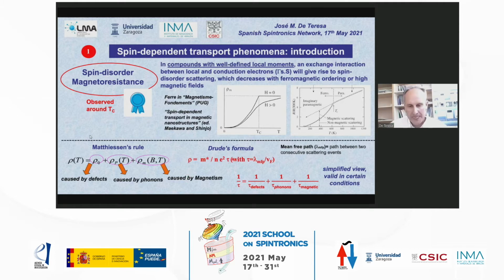To put it in simple words, if you apply Drude's formula for a free electron material, then the resistivity is determined by the effective mass of the carrier, the density of these carriers, the electrical charge, and the scattering time, with the scattering time being the quotient between the mean-free path and the Fermi velocity. The mean-free path is the path between two consecutive scattering events. So in a simplified view, which works in many cases, the inverse of the scattering time could have three different contributions: the contribution of defects, the contribution of phonons, and the contribution of magnetic origin.